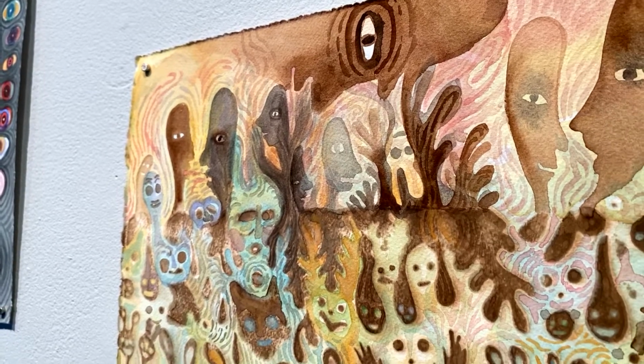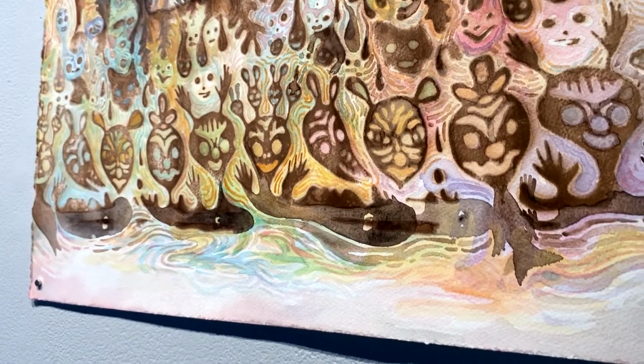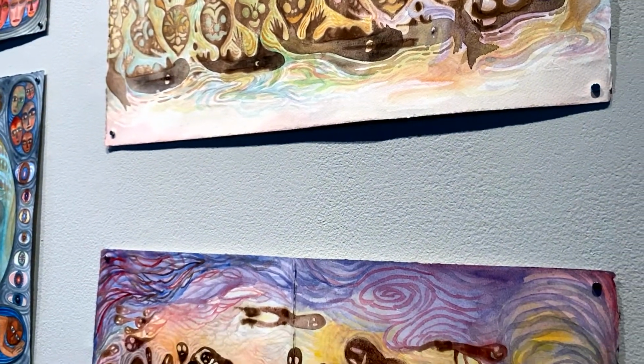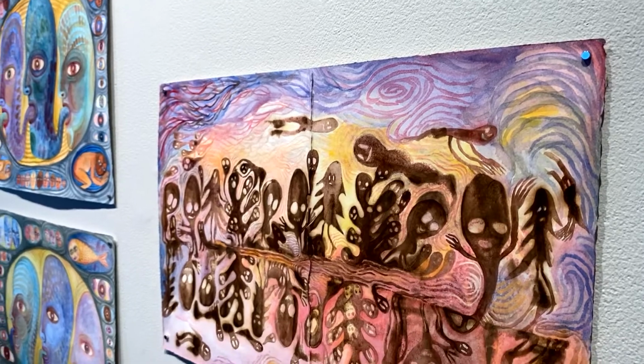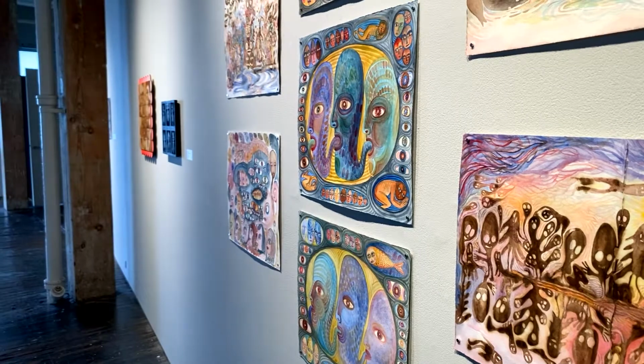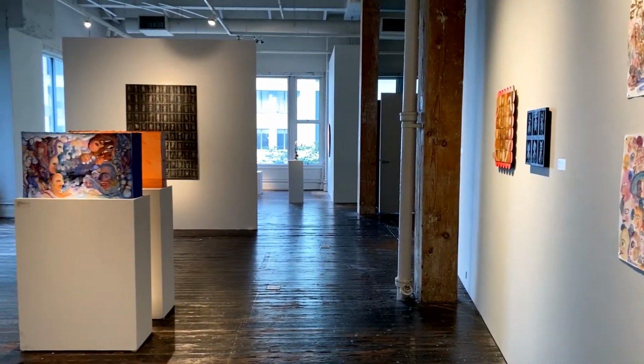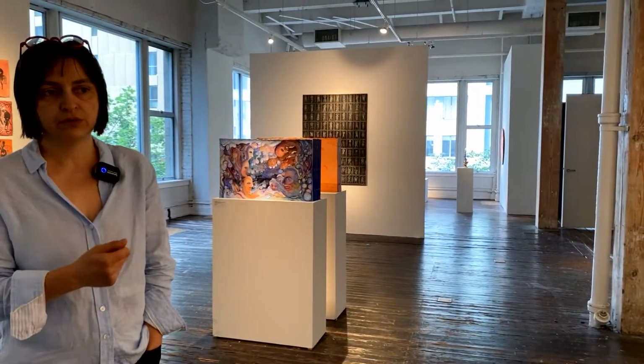Yes, I cover it with a buttercut vinyl. I cut into that, then I sandblast it so that there's a deep etch on it. Then we heat it back up in the glory hole, so it's super, super hot, and then we roll it on paper. The way it works is we do several rolls, and because the cylinder starts to become really soft and melts as we roll it, it torques, so the image actually changes with every roll.